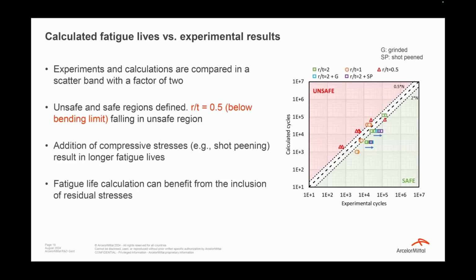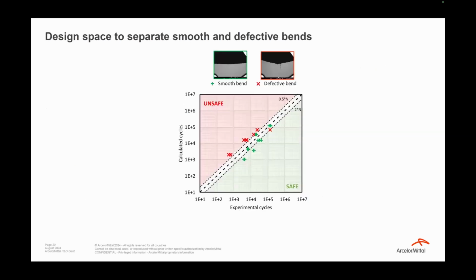So if we add the compressive stresses, so we had also some runs with shot peening and grinding that result in longer fatigue lives. But what we haven't done, but we plan to do, is the addition of the residual stresses. So since they're not added yet, simply they are shifted on the right more into the safe side. But of course, if you include the residual stresses in your linear elastic analysis, then it will be possible to get a better calculation so that they will be also close to the approximating line. So these calculations can really benefit from the inclusion of residual stresses.